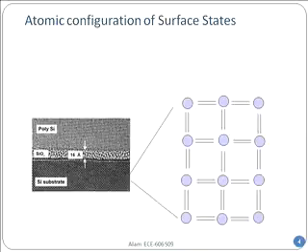Now, if you look at the silicon, you remember that silicon has a tetrahedral structure, right? And we pushed it flat onto the surface, and that is how we have drawn it. The circles are each silicon atoms in the crystalline phase, and the double lines are essentially the covalent bonds between silicon atoms. So you have 4 neighbors, a tetrahedral structure, and you can see that every atom in the planarized version still has 4 bonds. Of course, this continues up and down. Had it been bulk, this would have continued up and down. But just think about the row right on the surface. Then what would happen? This is what is going to happen.